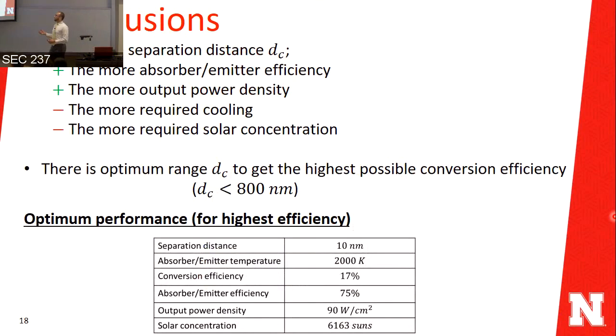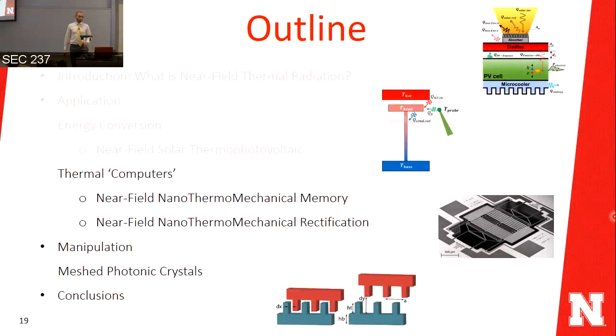So we can take from our research that the lower the separation distance, the higher the absorber efficiency you will get, and the more output power density you will get. However, you have two drawbacks: the increased rejected heat and the increased solar concentration. The optimum range efficiency-wise would be 800 nanometers. So if you would like to fabricate a system like this, you should target separation distances below 800 nanometers. And this is the highest efficiency possible. You notice that the separation distance is a tiny 10 nanometers, which is not practical. So that's one part of my dissertation research, targeting the energy converters.